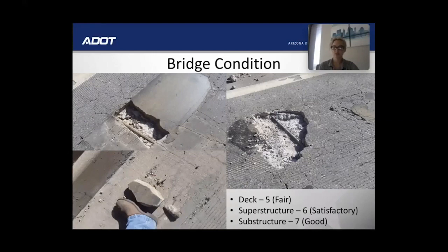Major findings from the bridge inspection report included extensive transverse and map cracking on the deck top. The deck underside exhibited transverse cracking with efflorescence, deep spalling, and exposed reinforcing bars. The girders experienced cracked welds, missing and loose bolts randomly at various locations. The condition ratings that were given were 5 for the deck, 6 for the superstructure, and 7 for the substructure.